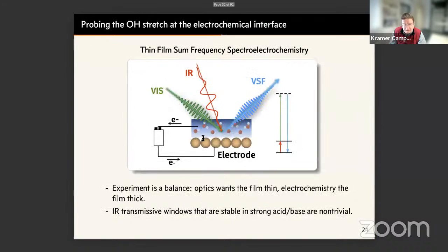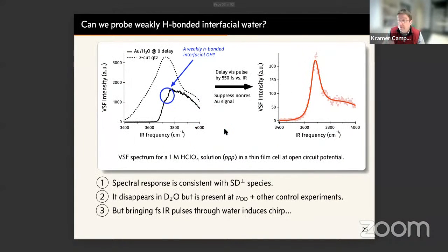So we need to bring an infrared pulse through a layer of water and reach the electrode. And of course, liquid water has lots of water, and this water absorbs at OH stretch frequencies. And what is happening is shown here, right? This is the spectrum of our infrared pulse before it passes through the water. And you can see quite clearly that none of the photons that enter the cell are actually reaching the interface at, say, 3600 wave numbers. It's all eaten away by water absorption.